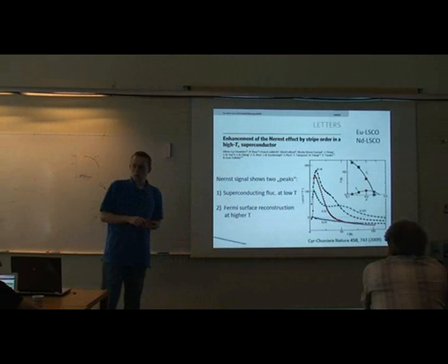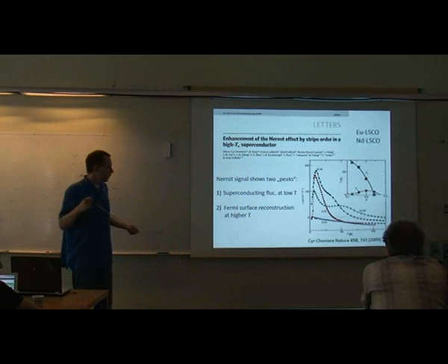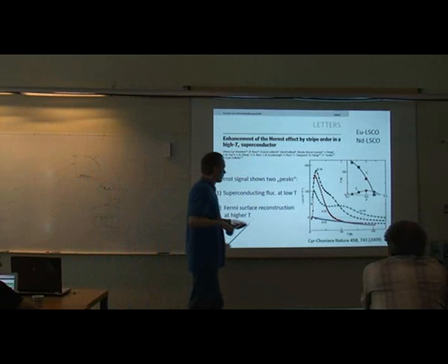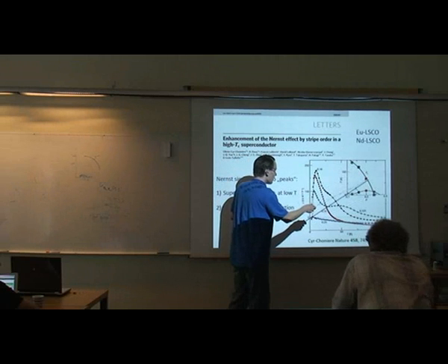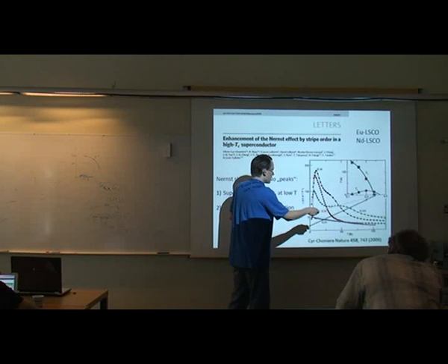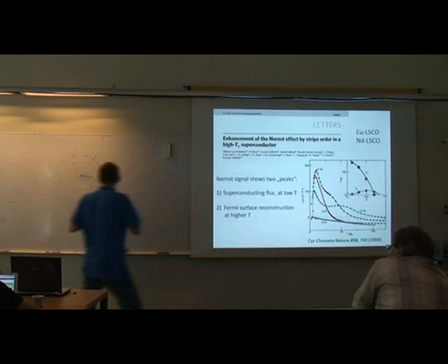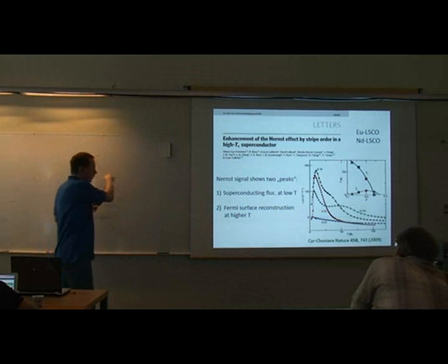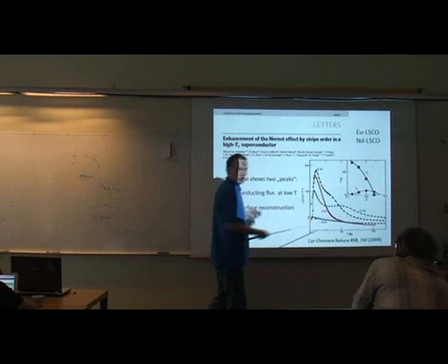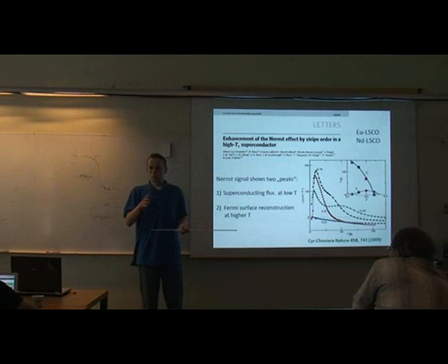When the Nernst signal goes negative, what does that mean? Yeah, that's another important thing to tell. So this is at the boundary. You see this T-mu is the temperature where this onset of this Nernst signal, which vanishes at this point. It's roughly equivalent to the point where the stripe order is not stable anymore. Yeah. And there you get a small negative and featureless signal. That's what I usually see, it's always in the background. That's what you observe when there's no broken symmetry and no fluctuating superconductivity.